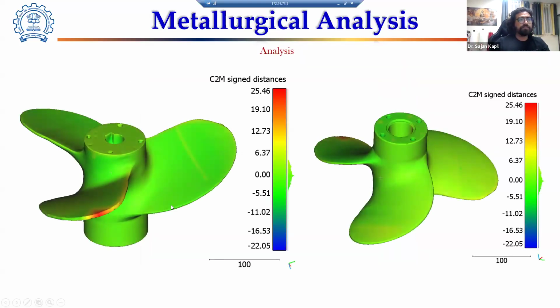After deposition, we scanned. This is the right view, this is the left view, I mean the front view and back view. There was no under deposition. Under deposition is blue. We see not very blue portion. Everything was mostly on the green. Correct? You see the distribution here. This is the green. That means some excess deposition, and this is the portion where it was very thin and we deposited extra material. We deposited extra deliberately because we need a nice grinding allowance so we can do the grinding of that tip, which gives it the right profile. So we didn't do that.